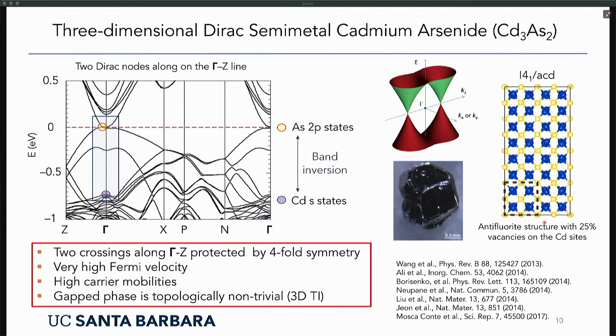Right, so the crystal structure is quite complicated. You can consider it to be based on an antifluorite structure, where 25% of the cadmium sites are not occupied. And the outlined part here is the antifluorite unit cell with the missing cadmiums. And that's repeated throughout with cadmiums missing at different positions, and it makes this very, very large unit cell. And the other thing I wanted to mention here, it belongs to this space group, which is a 4/mmm point group, and that's a centrosymmetric point group. So it's not a Weyl semimetal because it has a center of symmetry.